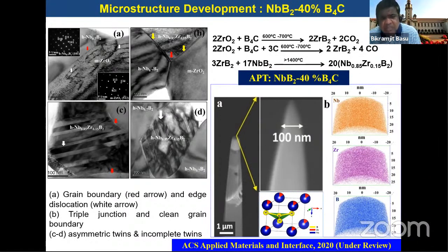The formation of this particular intermetallic compound can be explained by the sintering reactions, which have been shown. Unfortunately, we could not do a thermodynamic analysis to show you that delta G is negative for these particular sintering reactions, but we certainly believe this is what the sintering reactions are. Since it is a new intermetallic phase, we have used state-of-the-art techniques like atom probe tomography to see the distribution of niobium, zirconium, and boron in this phase. Based on all this transmission electron microscopy, selected area diffraction pattern, and APT-based analysis, we have found out that this could be the possible crystal structure of this niobium 0.85 zirconium 0.15 boride compound.